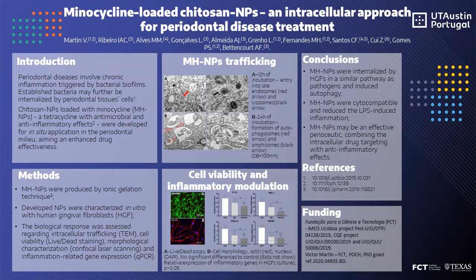PG can survive inside the lysosomes and then escape to cytosol or even to neighboring cells. When these nanoparticles follow the same pathway, they can deliver minocycline inside the lysosome, and this functional autophagy activation can prevent PG from escaping. Moving on to cell viability, nanoparticles did not provoke cell death, and no differences regarding cell morphology were detected, despite the autophagic induction.